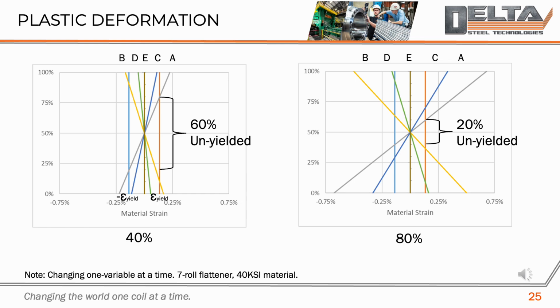The second chart represents a case with 80% deformation. Here, the penetration is greater, and the unyielded zone is reduced to 20%. This means a larger portion of the material has undergone plastic deformation, permanently relieving residual stresses and achieving a much flatter and more stable result. The key takeaway is that increased deformation leads to a smaller elastic zone and greater material stability. By carefully controlling penetration and strain through the leveler, we can optimize the balance between deformation and flatness. The results demonstrate how achieving higher levels of plastic deformation, while maintaining precise control, produces a more consistent and flat product.